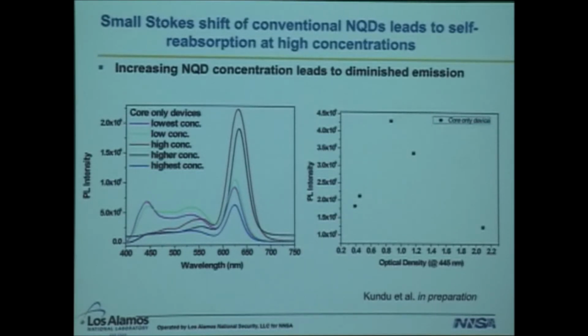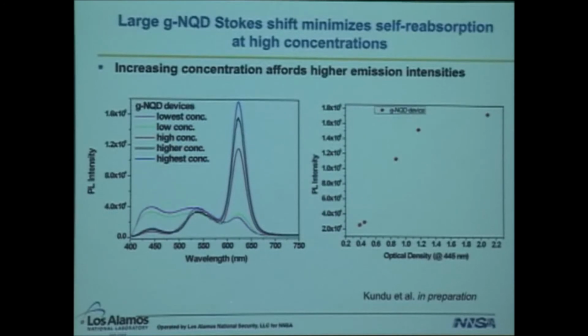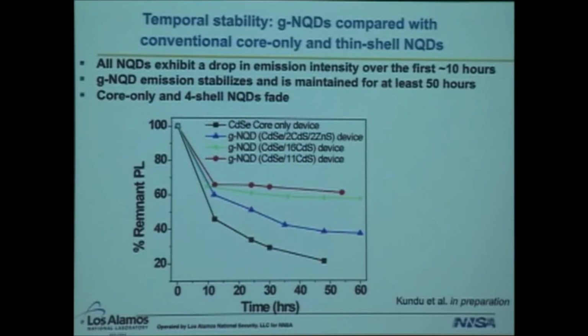In the case of a core-only phosphor material, you can keep increasing the number or the density or the concentration of quantum dots in your slab of quantum dot plastic in your device. And initially, you increase the intensity that you're getting out. But actually, as you keep increasing the concentration of the dots, you get self-reabsorption effects. So the dots reabsorb their own light. In the case of giant dots, we increase to the same concentration, and so normalize at the same wavelength. And we see that we're not having those problems. So that's good news for use of giant dots as phosphors.